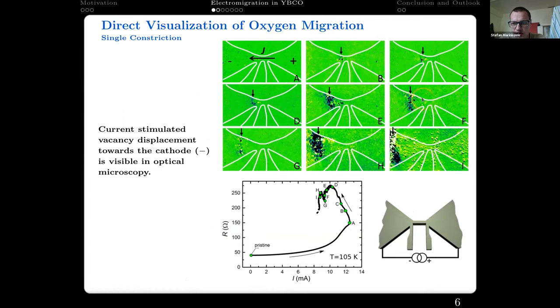And it's strongly directional towards the left. The cathode is on the left side and the anode on the right side. And you see that the front propagates clearly to one side. The pictures here correspond on this resistance versus current curve to the points indicated here. This curve is taken during the electromigration, which takes a course over several hours.